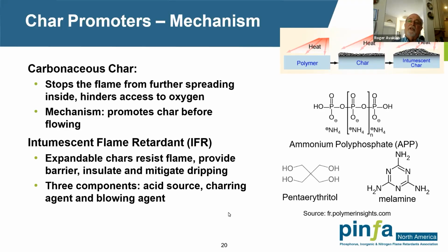And what that does is obviously this char prevents materials from dripping. It acts as a barrier from oxygen coming in and for flammable gases going out. And particularly when it's intumescent, you get this foam structure, which acts as a thermal insulator. So you've actually got several items going on here. These expandable chars resist the flame, and as I mentioned before, provide a barrier and insulate and mitigate the dripping behavior. Again, the three components that are needed for an intumescent char are an acid source, like the ammonium polyphosphate, which gives an acidic material upon heat, a charring agent, typically some hydroxy-containing material, as in this example, pentaerythritol, and then some type of blowing agent, typically melamine or some other kind of nitrogenous material that typically gives off nitrogen upon decomposition.